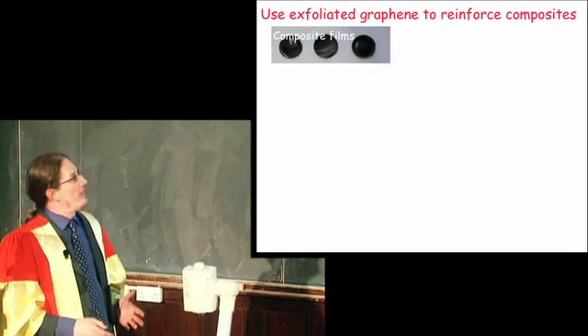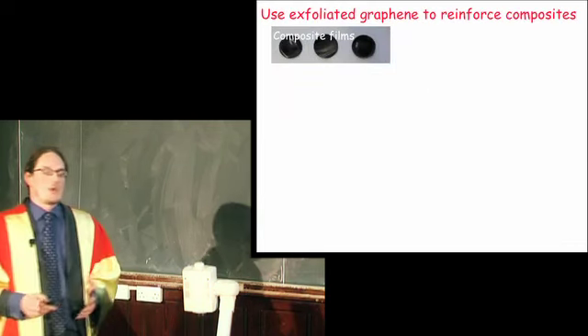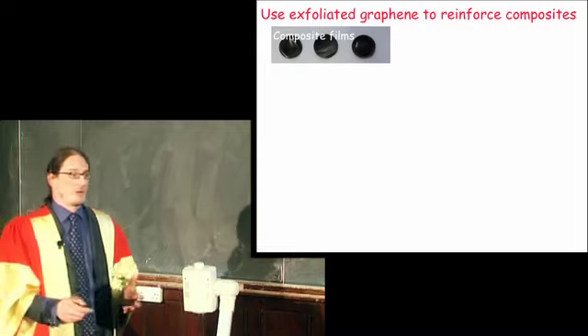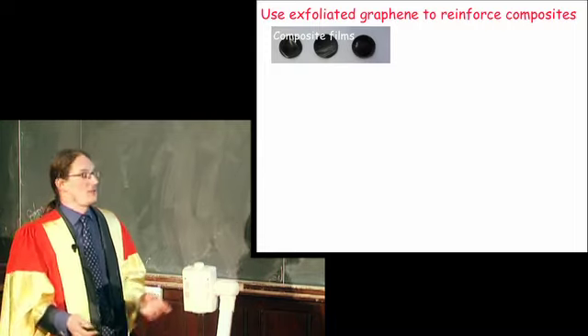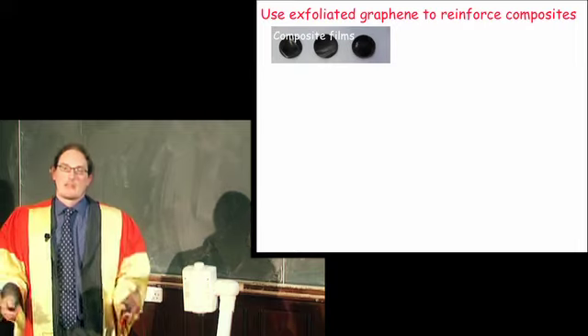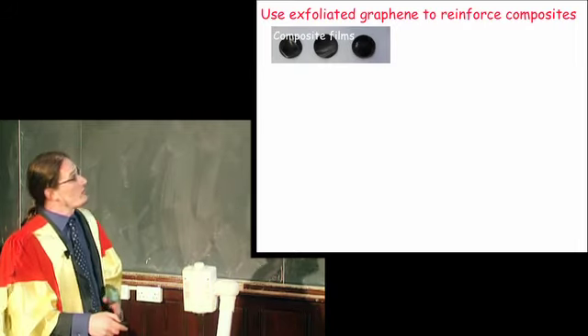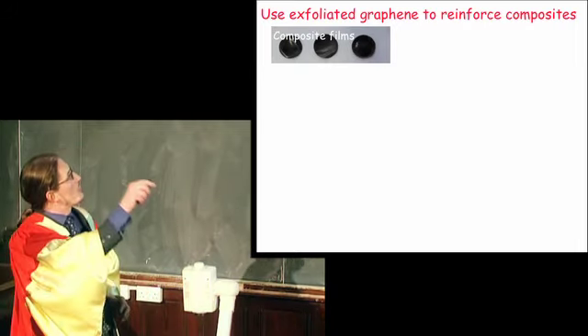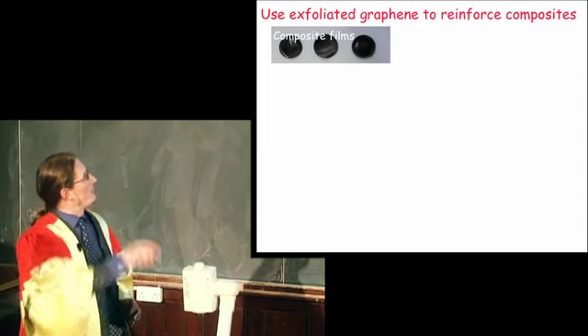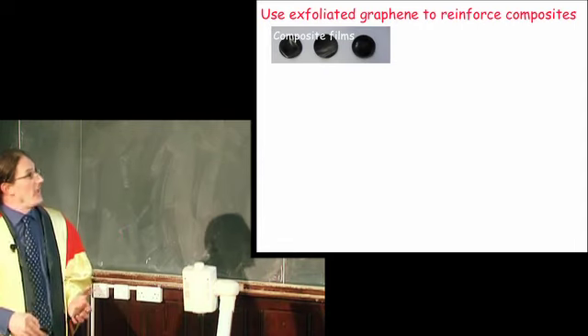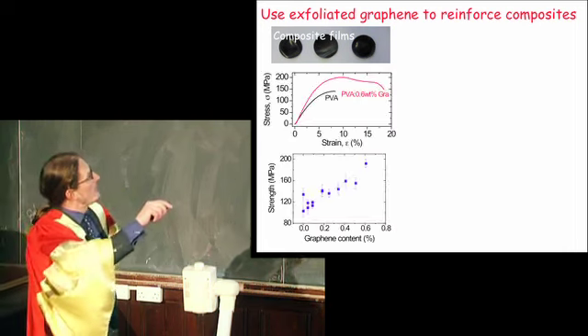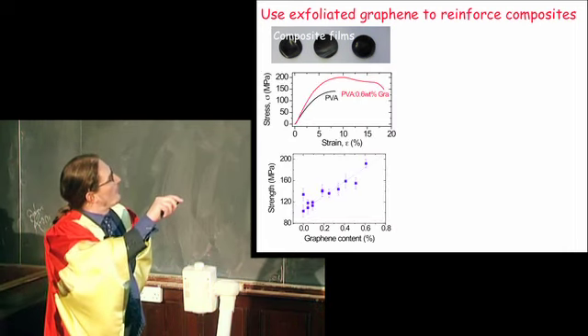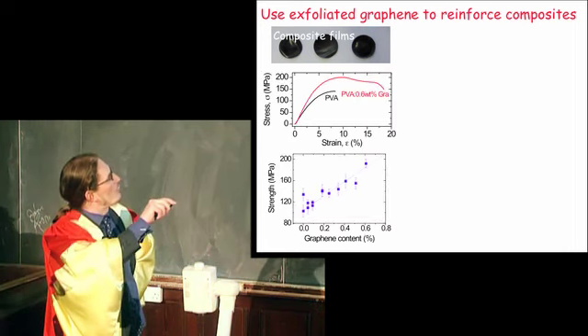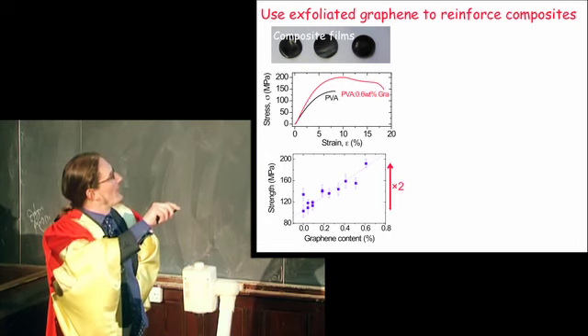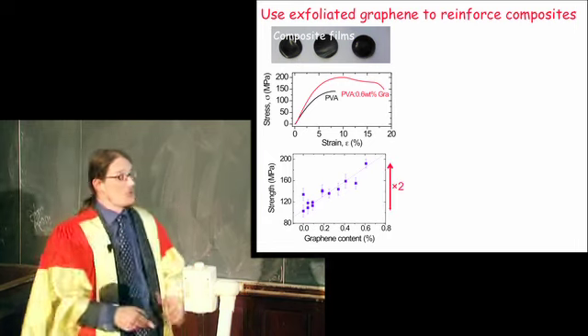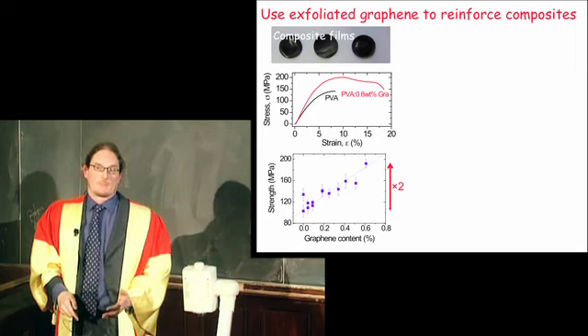Can you do anything with this stuff? Well, graphene, along with carbon nanotubes, is the strongest material known to man. So one might imagine that if you put it into a plastic, it will make the plastic stronger. Using our processing technology, we could put graphene into plastics. These are composite films, and we could measure the mechanical properties. What we found is that as you add graphene to a plastic, the strength increases linearly until at about half a weight % of graphene, you've doubled the strength of that plastic.